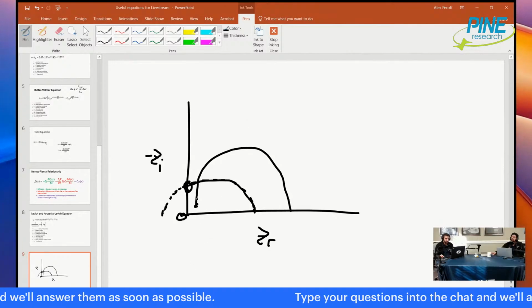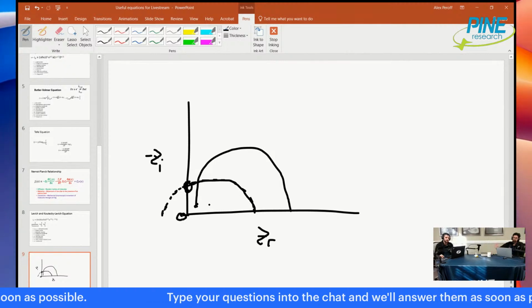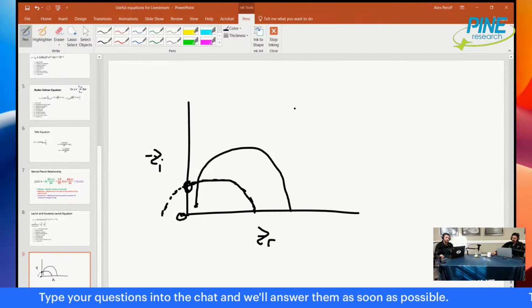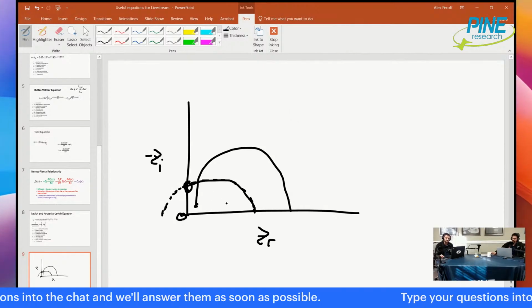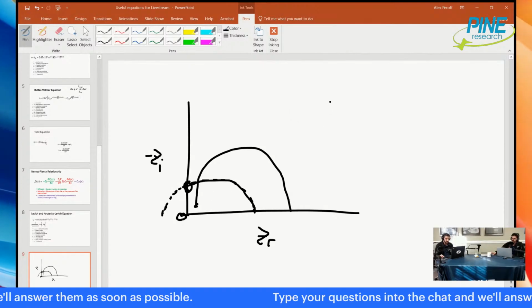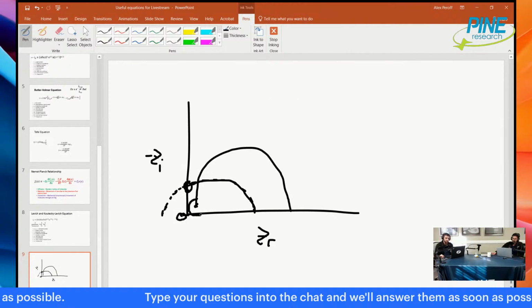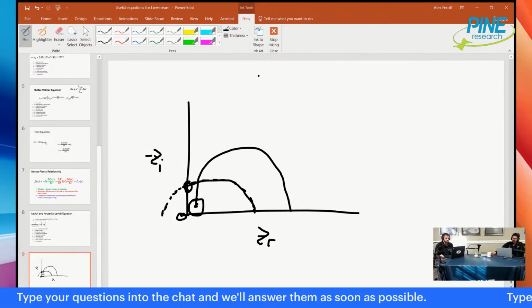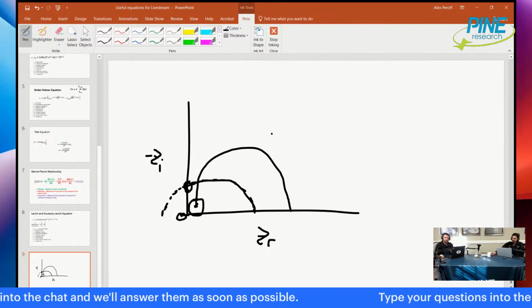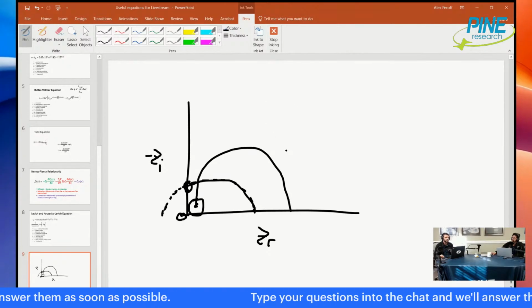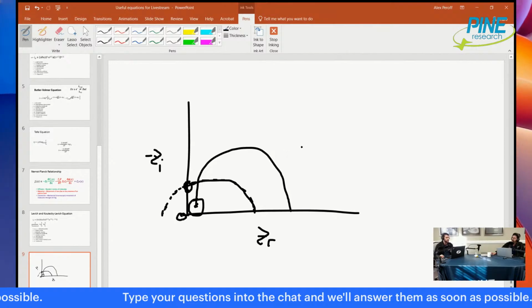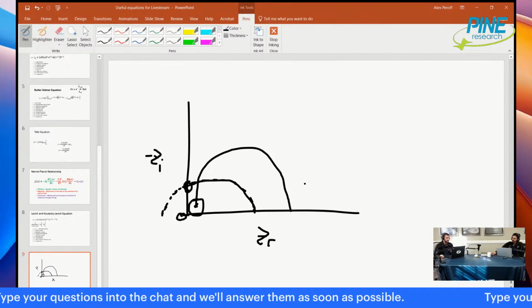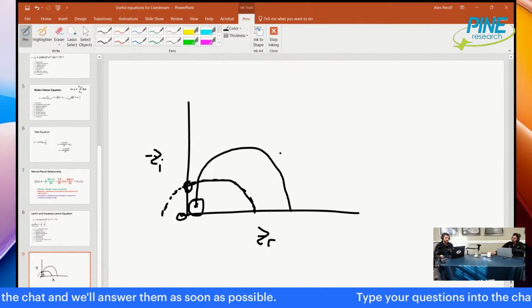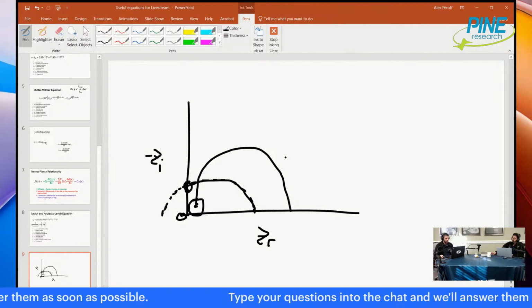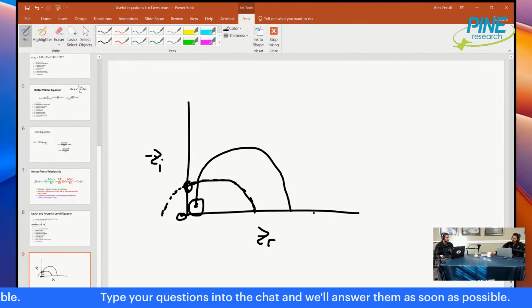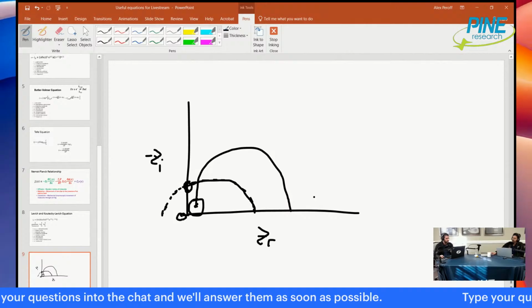So it means you have a charge transfer process with a very, very small capacitance. And to probe very small capacitances, you have to use really high frequencies because otherwise the impedance of it is so great that the capacitor is bypassed and virtually unmeasurable. It's pretty rare, but it's possible to have a very fast process with a very small capacitance and a very short time constant. Sometimes that can happen with solid state systems, because you need fast frequencies to probe them since the time constants are so small.